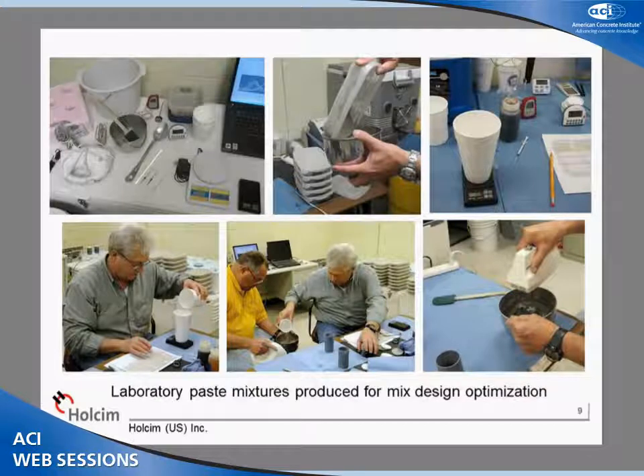What I'd especially like to concentrate on is the use of laboratory paste mixtures. Very, very quick and easily executed process in which we actually model the paste-only content from your envisioned concrete mixture. No aggregates, just cementitious materials, mixed water, and chemical admixtures. This is a very convenient way to understand the effects of different chemical admixtures, their dosage rates, and their interaction with particular materials of interest. And the equipment used is very simple and easily acquired. It's a routine thing. What we do is pre-weigh the powdered ingredients.